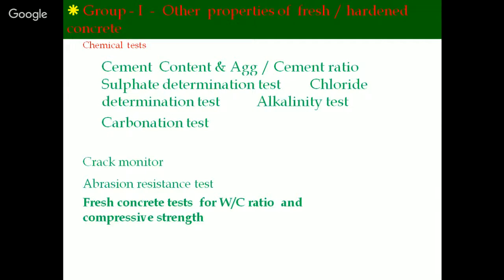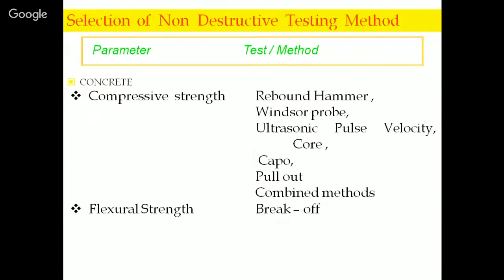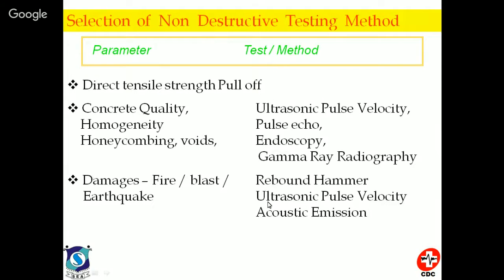You can have a crack meter to observe crack monitoring, and abrasion resistance. Now you can find out the other properties also. So these are the tests, basically parameters used for compressive strength. We have the rebound hammer, Windsor probe, ultrasonic pulse velocity and core test, CAPO and pull-out test, and combined methods also. To determine the flexural strength, we have the break-off test. Direct tensile or pull-off test, basically, yes, break-off test again. For concrete quality, homogeneity, honeycombing, you have ultrasonic pulse velocity, pulse echo, gamma ray radiography test. Then for damage from fire, blast, earthquakes, we are using the rebound hammer, ultrasonic pulse velocity and acoustic emission test there.